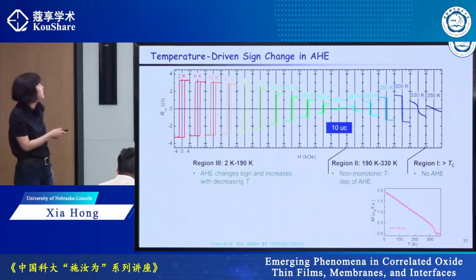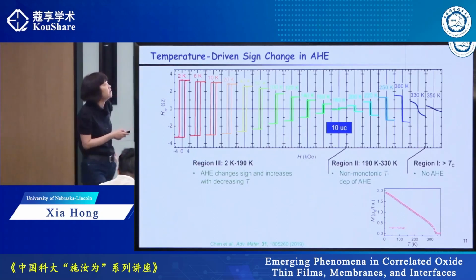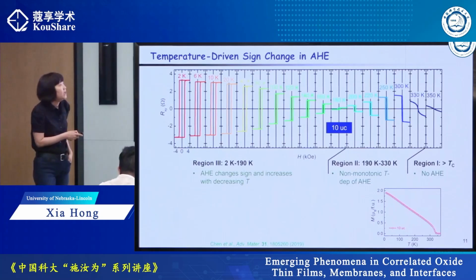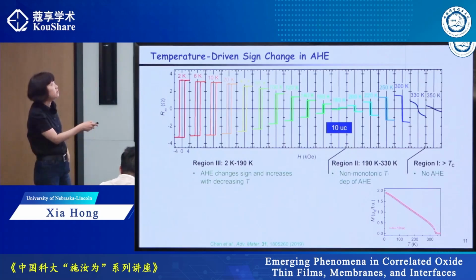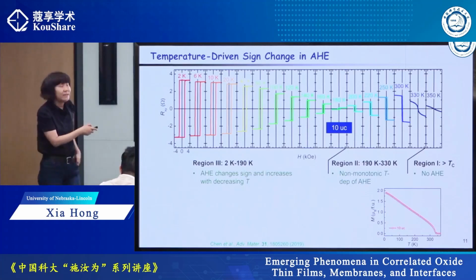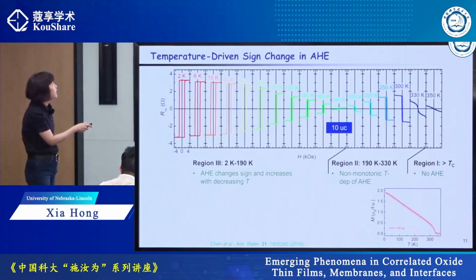Previously, I showed you that this square shape reflects that the film has a perpendicular magnetic anisotropy, but the temperature dependence of the anomalous Hall effect is very strange. So it's non-monotonic, right? If you look at the high temperature, first you can see that we have this rapid increase of anomalous Hall resistance. This is because the magnetization is actually increasing rapidly. And then it reaches a maximum and starts to go down, goes to almost zero at 190 Kelvin. It re-emerges again at a low temperature.